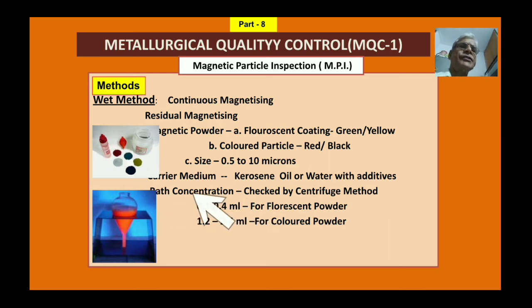Then the bath concentration. Whatever magnetic bath you are making, whether in kerosene or in water, it has to be checked for its strength by the centrifuge method. There is a centrifuge tube, and the tail part of it is graduated in milliliters. If it is a fluorescent powder, then the particles should settle after half an hour to 1 hour at 0.1 to 0.4 milliliter. If it is settling in this range, it means your strength is okay. In case of colored particles, red or black, it has to settle 1.2 to 2.4 milliliter. So this way you can check the strength of the bath, whether it is okay or not.